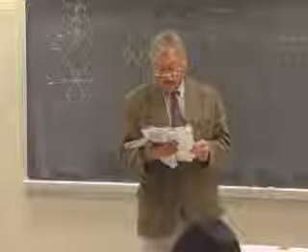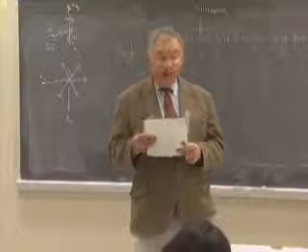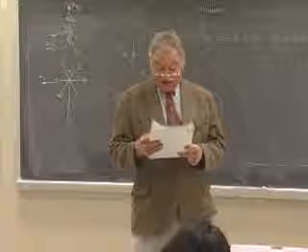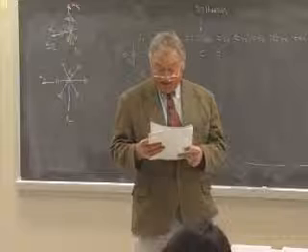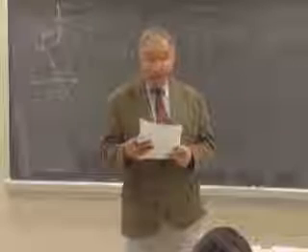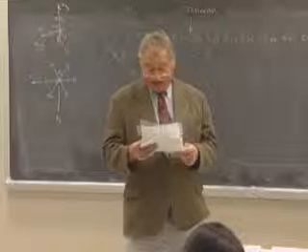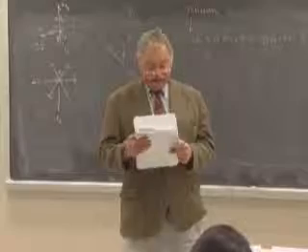For cubic, a rather remarkable result. There are 3 independent compliances, but cubic crystals are not elastically isotropic. They are anisotropic. And it's just the nature of the tensor that requires that.